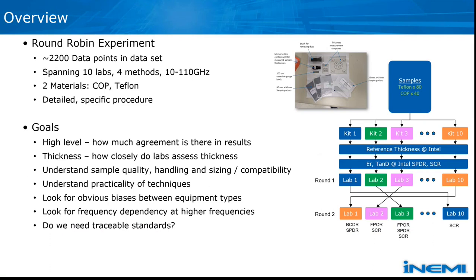The experiment concluded with measurement of over 2,200 data points in the data set, spanning 10 different labs using these 4 methods and covering frequency ranges from 10 gigahertz to 110 gigahertz. This turned out to be a lot of data to collect. There are 2 materials that we focused on out of this experiment. Again, the COP and Teflon. We provided a very detailed and specific procedure as part of this kit to allow, as much as possible, the labs to perform essentially the same set of material handling procedures to try and eliminate as much as possible variabilities between the measurements. So these kits were created, and we had 10 kits.